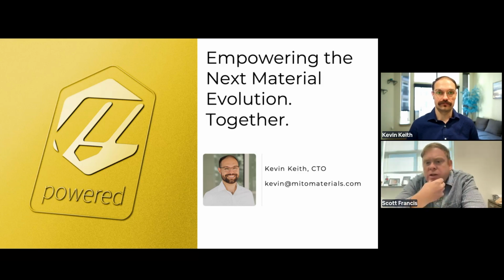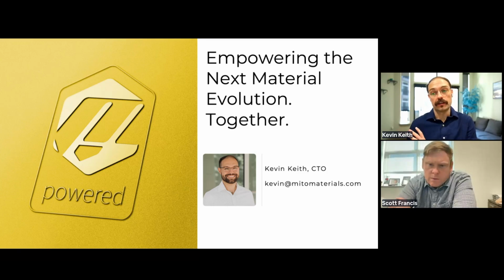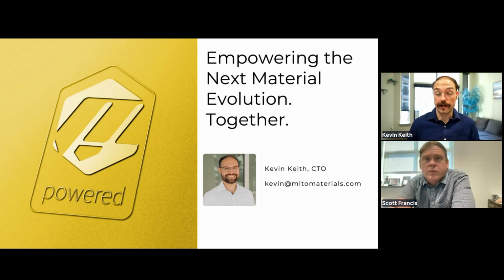Does it make a difference if we are dispersing large particle size graphene with a shear mixer in epoxy? It depends on the viscosity of that epoxy. For instance, yesterday I just had a 7-hour pilot where, on the shop floor, mind you, we were dispersing our functionalized product into an epoxy. Typically, this epoxy is within the 12 to 18,000 centipoise. When it's that thick at room temp, we generally say you're going to have to 3-roll mill this because it's like honey. Because we heated it up, it had a viscosity of probably 800 centipoise, maybe 1,000. So it was a lot thinner, and we were able to just shear mix it, and it reactively dispersed. It was very, very beautiful.